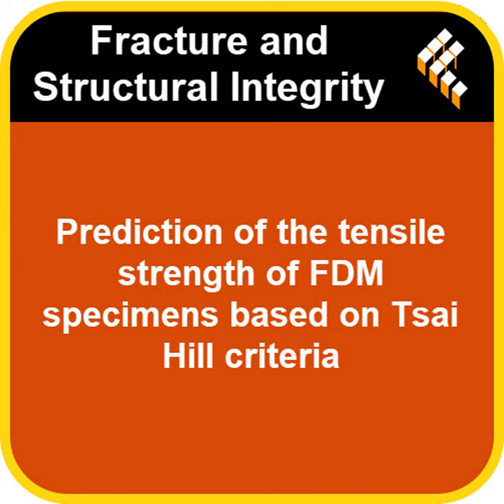Fascinating. So it's like the angled structure was better at handling that sliding force. It seems so. That interlocking pattern provided more resistance to the layers sliding past each other, and figure 12 in the study apparently shows these different shear failure patterns quite well. It's really amazing how the failure mode changes so much depending on the force and the print structure. And it sounds like for shear forces, generally speaking, adding that contour is a good idea. Absolutely. That was a clear takeaway from the shear tests.